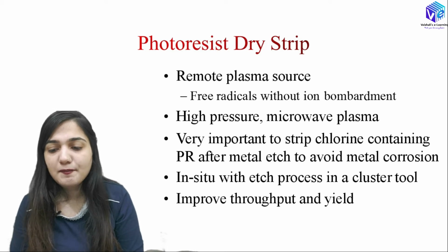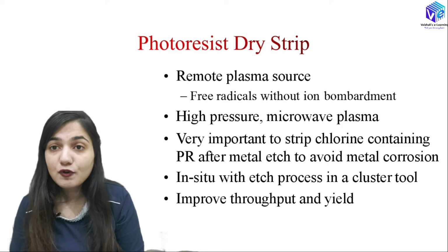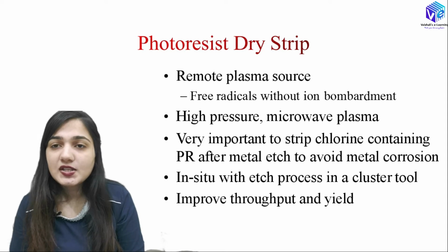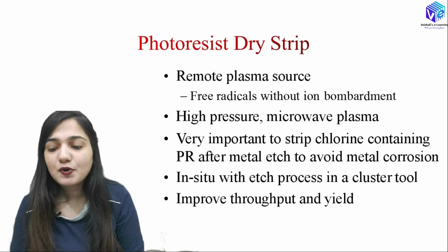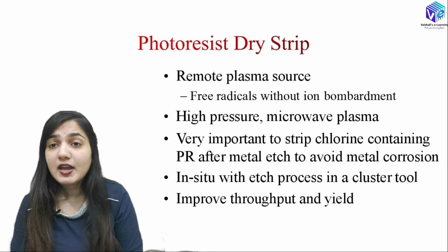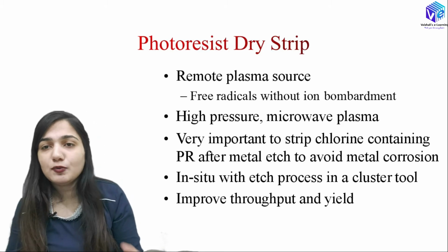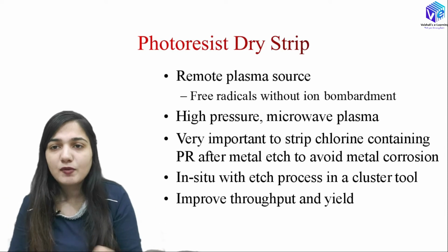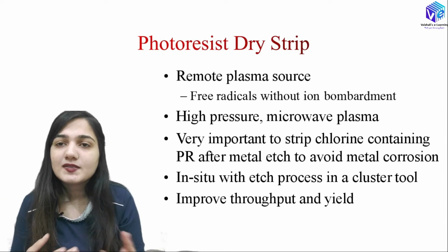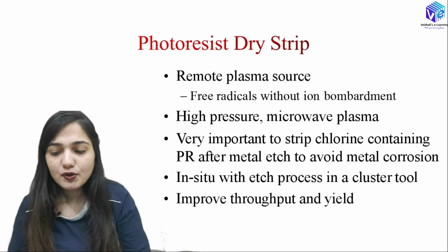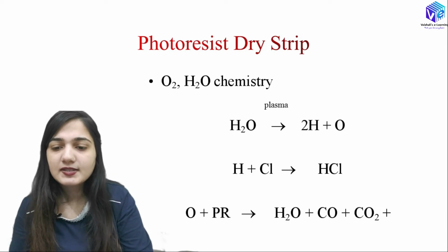It is very important to strip out chlorine-containing photoresist after the metal etching to avoid metal corrosion. I hope you understood this. I have already explained this. This process is done in situ with the etch process in the cluster tool only. So wherever I was using the metal etching process, in situ means in the same place, in the same equipment, I am doing the photoresist dry stripping as well. So it will improve the throughput as well as the yield.